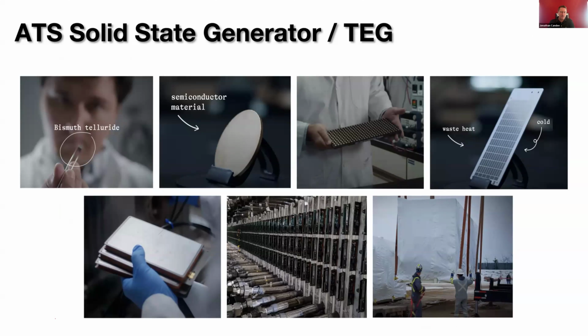So at ATS, we spent the last 10 years developing this product set. We've taken bismuth and tellurium and doped this with additional minerals in a very specific formulation for a positive and a negative semiconductor material. We put that material through an SPS process, which is think heat and pressure, to drive a specific formulation of our semiconductor material. We then metallize that and cut that into pellets. Those pellets are then put inside of a cartridge. I'm actually holding one up right here, about the size of an iPad mini.